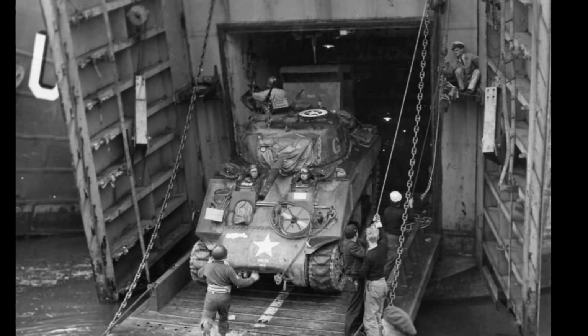LST-531 hit a mine off Utah Beach during the Normandy invasion. The explosion tore a massive hole in her bow, flooding the tank deck. In a Liberty ship, that kind of damage typically led to catastrophic crack propagation and rapid sinking. LST-531's welded hull contained the damage. The crack didn't propagate beyond the immediate blast zone. She stayed afloat long enough for her crew to beach her, and most survived. The ship was later repaired and returned to service.